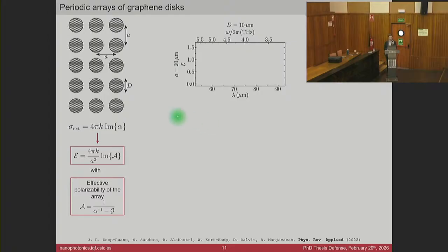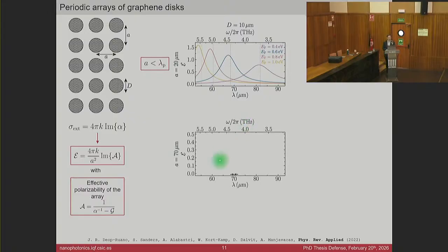Let's analyze some results for a period that is twice the size of the nanostructure for different levels of doping, different Fermi energies, and what we see is some broad resonances that actually resemble a lot the localized plasmons. Indeed, if we plot with dotted lines the resonance wavelength of these plasmons, we see that they coincide almost perfectly with these resonances. And note that this occurs for a period that is smaller than the resonant wavelength of the plasmon. However, if we move to the opposite limit, in which we now have a much larger period that is 7 times the size of the diameter, we plot for the lower level of doping, we see some similar results, but as we increase the level of doping, the resonance wavelength is going to cross the value of the wavelength that matches the period.